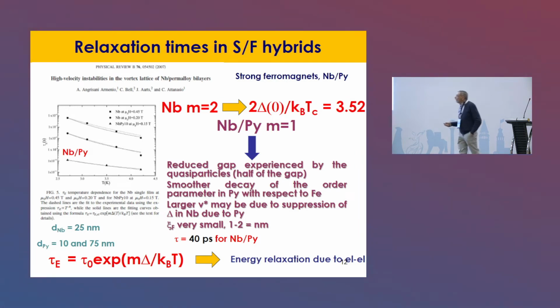In both cases, the temperature dependence of the relaxation time was exponential. In the case of niobium, this is tau here, the factor m equals 2, as it should be, because niobium is a typical BCS superconductor. In the case of permalloy, we also have an exponential behavior, but with m equal to 1, so a sort of reduced gap: on average, the system experiences a reduced quasi-particle gap.